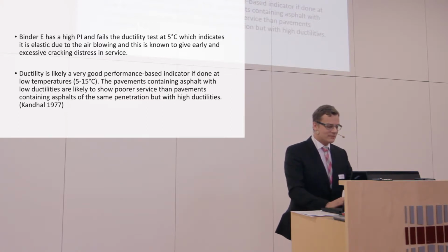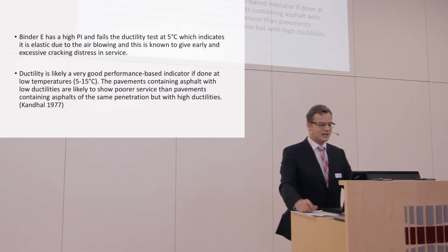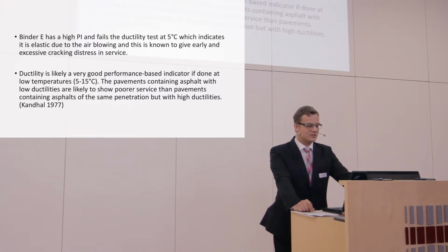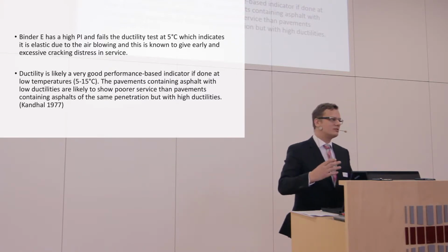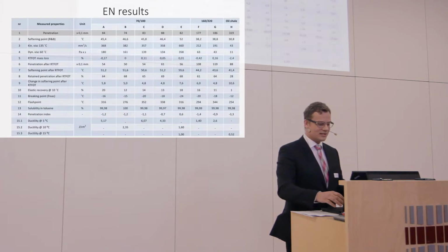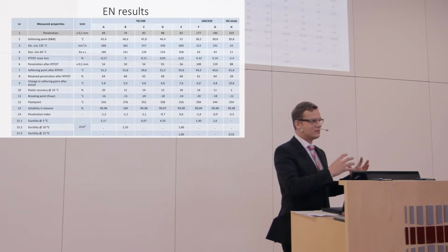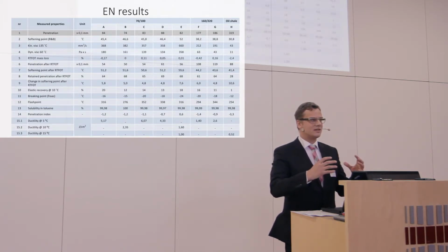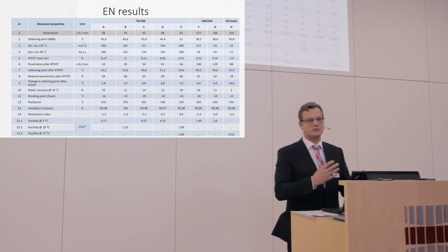Also, ductility is likely a very good performance-based indicator if done at low temperatures, around 5 to 15 degrees. Pavements containing asphalt with low ductilities are likely to show poorer service than pavements containing asphalt of the same penetration but still high ductilities. So these are the very good literature points we can point out when we look at this table, and afterwards you can see that these points are true.